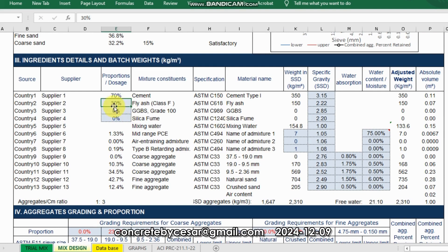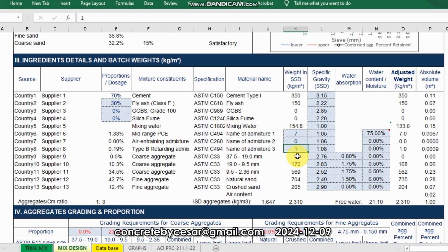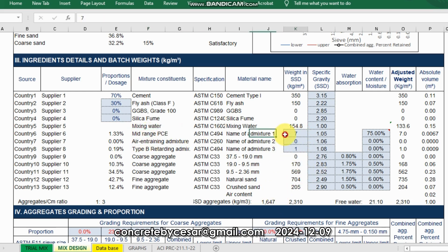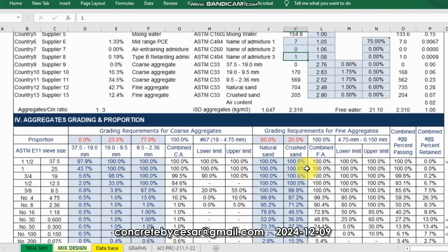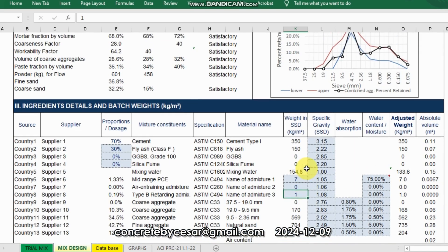This is your 30% fly ash, which is 150 kg by the way. You can use mid-range PCE. If you feel you need to prolong the workability, you can add 1 kg of retarder. Normally this is what I do instead of a viscosity modifying agent — just mid-range PCE plus retarder. So that's it for today.